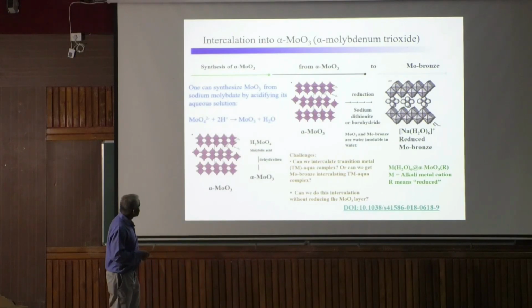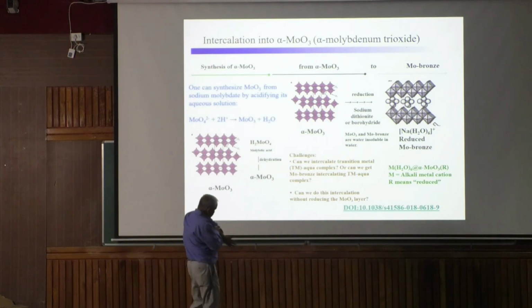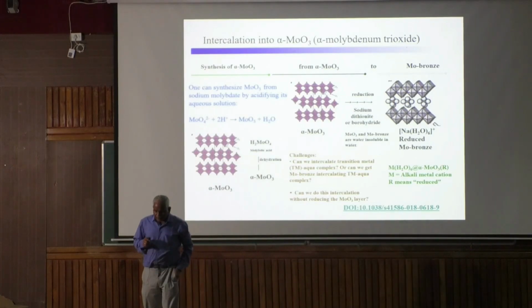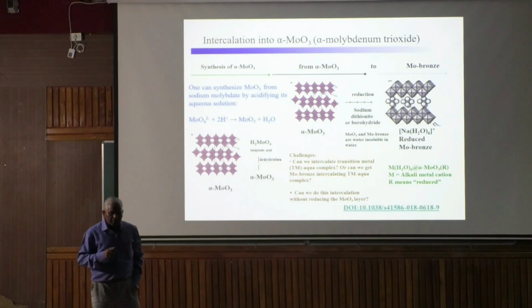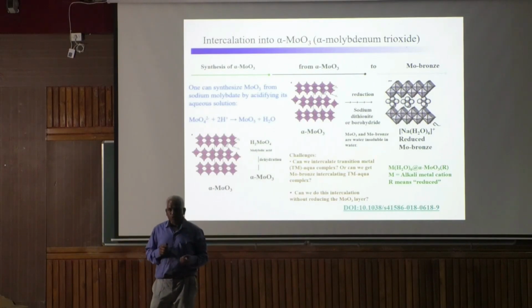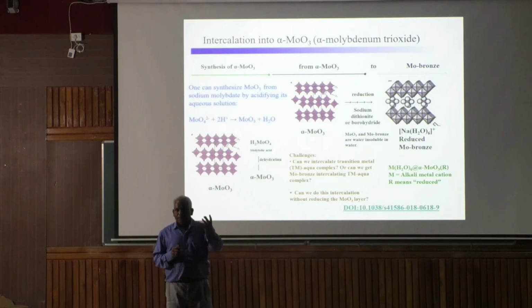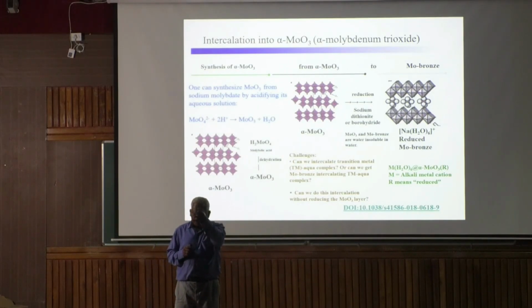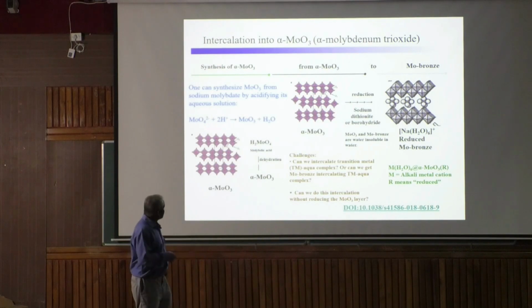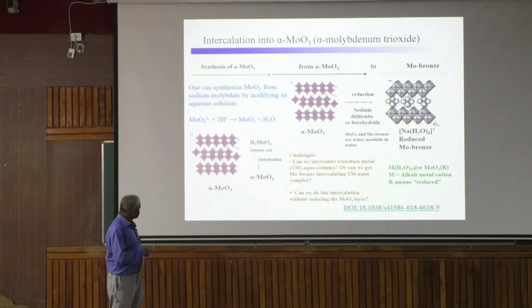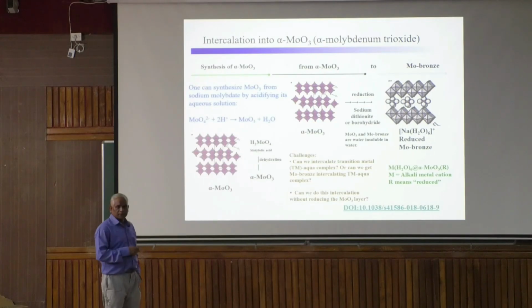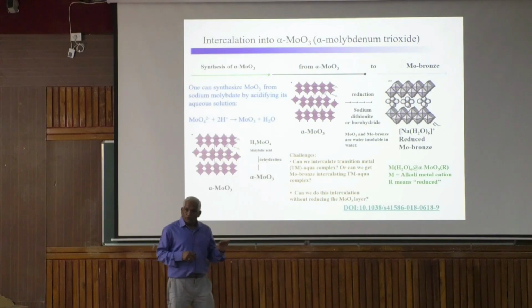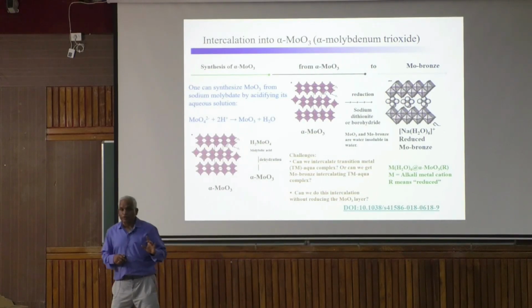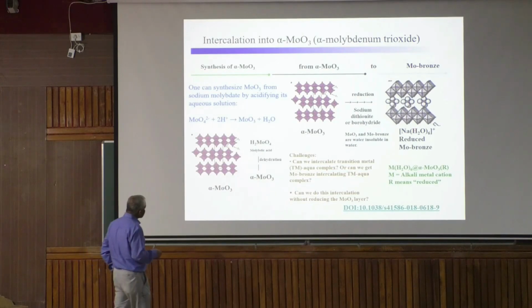Now again I have to thank crystallography, because by crystal structure we discovered something very interesting. What is that? This is the story of intercalation in MoO3. Let me tell you, because we do it in our MSc class practical, and there's one test called the molybdenum test. Sometimes we do a test for tungsten. For the molybdenum test, let's say you take sodium molybdate in water, highly water soluble, and dropwise you add hydrochloric acid. After some time you get some precipitate settled at the bottom. That is nothing but molybdic acid, isn't it? This molybdic acid is very well known. If you heat it, you get MoO3, molybdenum oxide. Molybdenum oxide has alpha MoO3, epsilon MoO3, a metastable phase, and a hexagonal MoO3, another state. But the thermodynamically stable state is alpha MoO3.